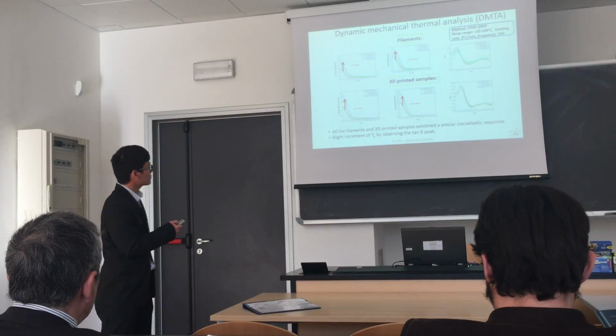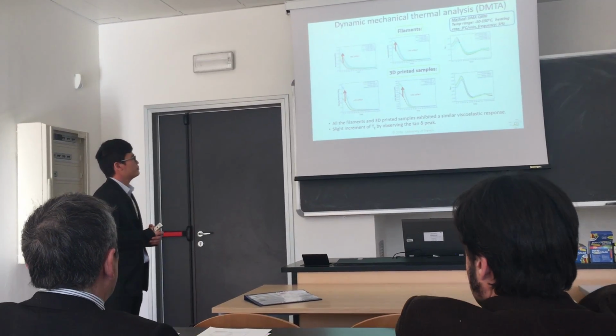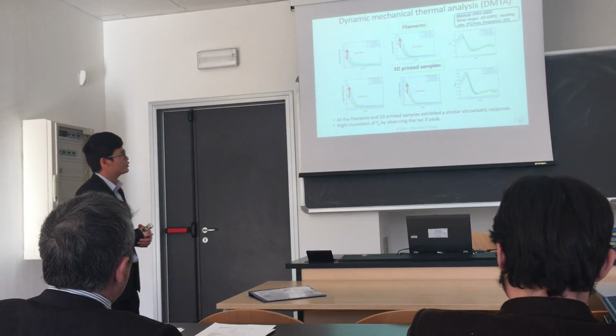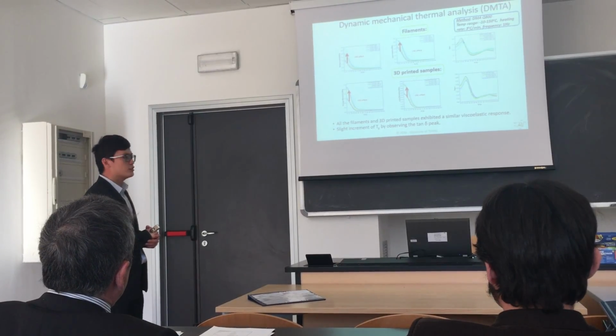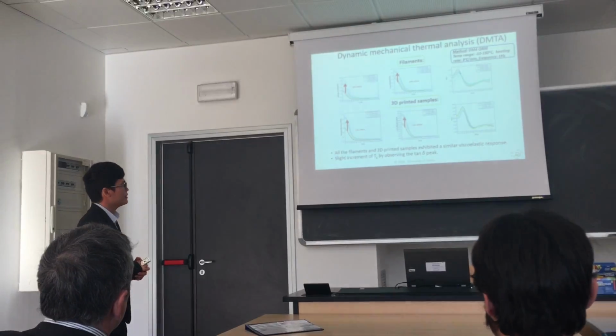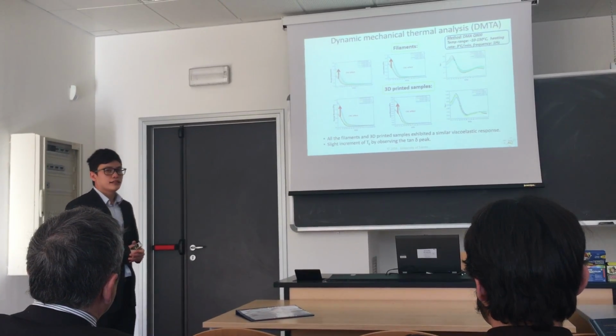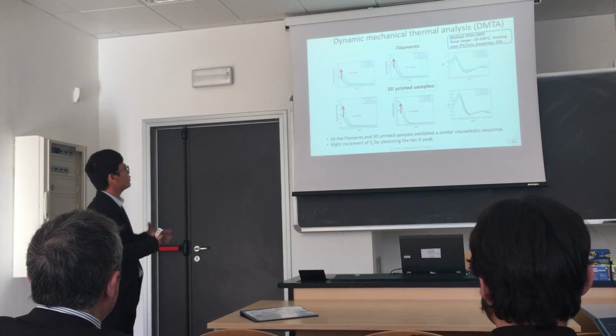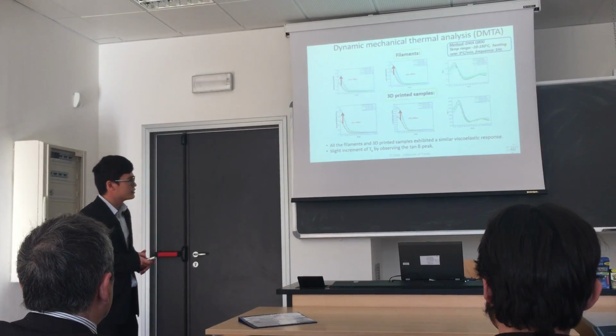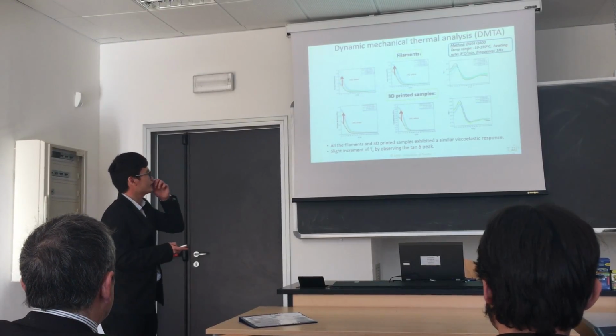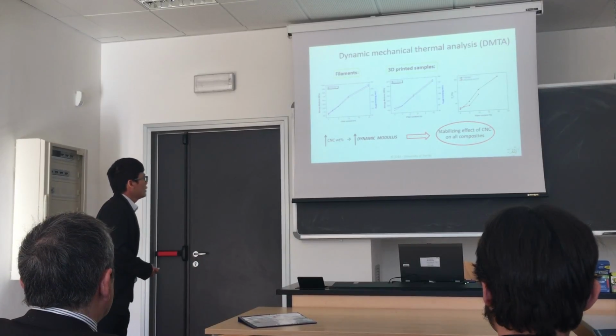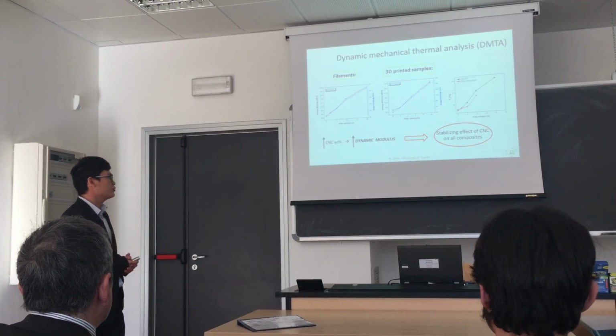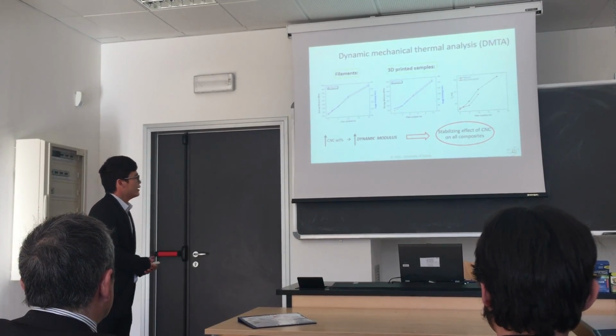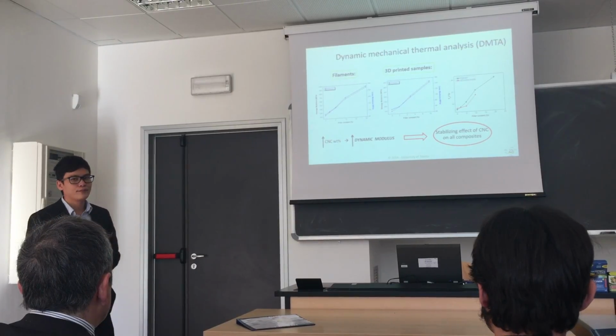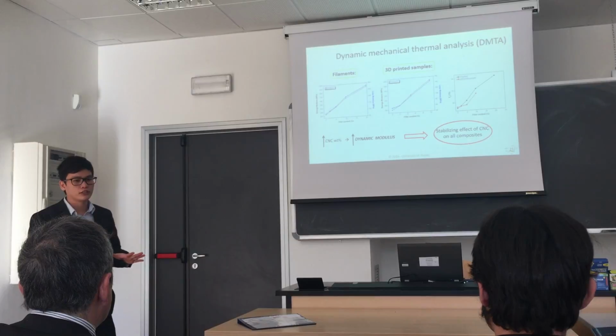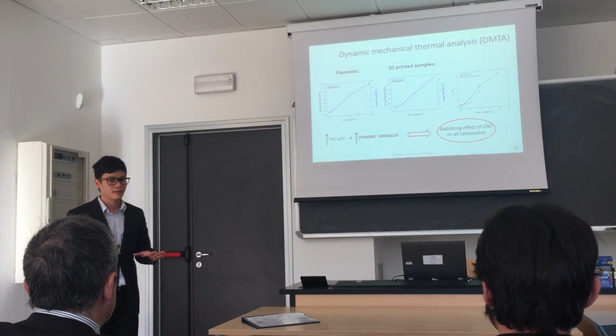during the crystallization. And here is the comparison of the dynamic mechanical thermal analysis (DMTA) of the filament and the 3D printed samples. We can clearly see that all the samples display similar viscoelastic behaviors, and there was a remarkable enhancement of the storage modulus, the loss modulus, and slight increments of the Tg, observed from the peak of the tan delta on the right side. So the introduction of the CNC leads to an increase of the dynamic modulus, and these results prove the stabilizing effects of nanocellulose on all the composite samples, regardless of the processing methods.